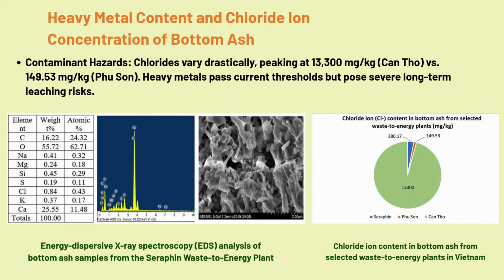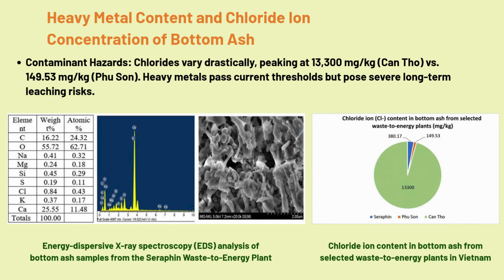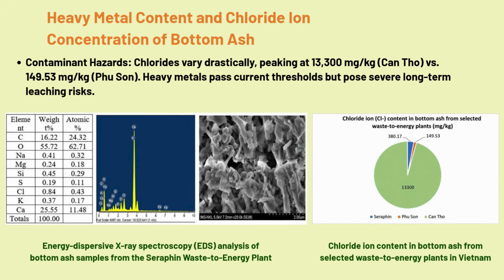The pie chart highlights a significant difference in chloride concentration among the three plants. Can Tho recorded the highest chloride content at about 13,300 mg/kg, while Phu Son has the lowest value. Although relative concentrations of heavy metal remain within current regulatory limits, their total content is still relatively high. Without proper treatment, they may gradually leach into soil and groundwater, posing long-term environmental risks.